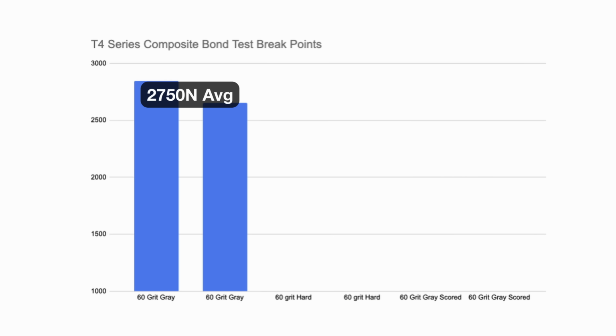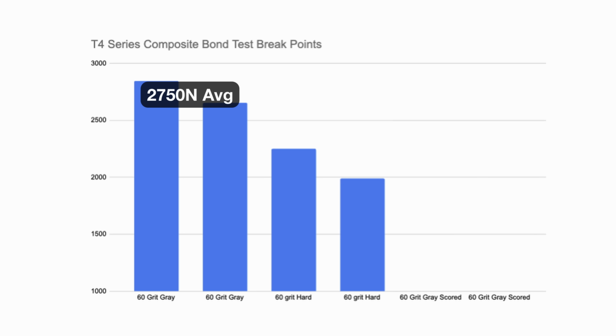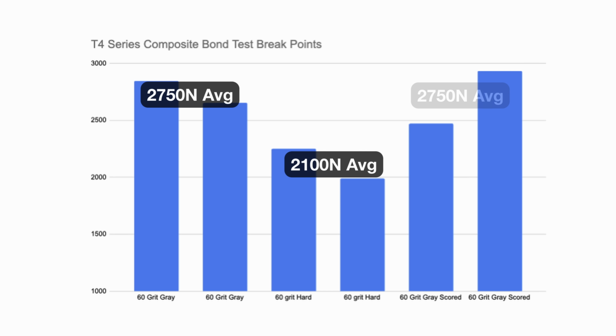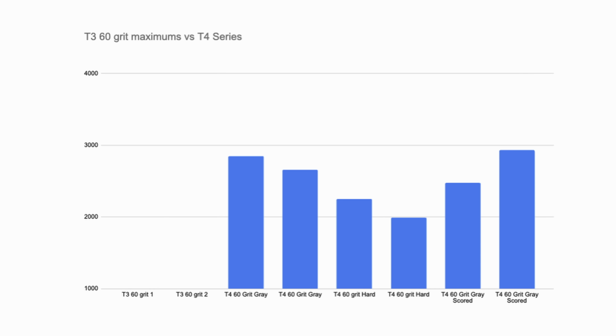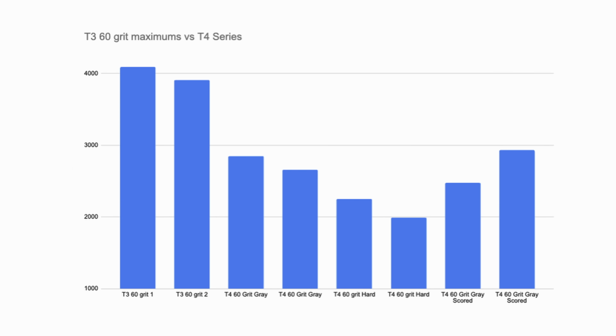The 60 grit gray averaged 2,750 newtons. The 60 grit hard sanding averaged about 2,100, and the 60 grit gray with scoring averaged about 2,750, just like the first, though with a much wider deviation between the two samples, so we've got less consistency when scoring is involved. All 6 of these tests were far worse than the 4,000 newton average from the first 2 60 grit tests. Something is consistently off here, and I think I know what it is.